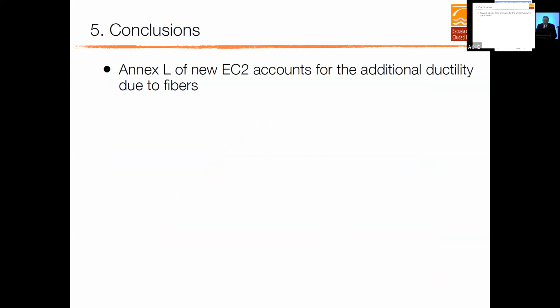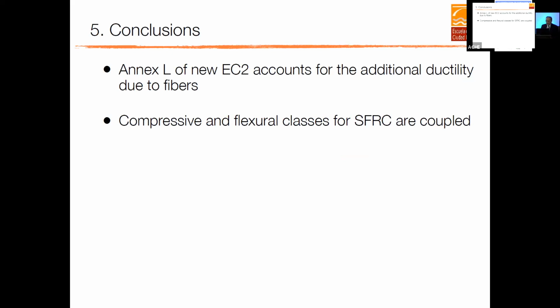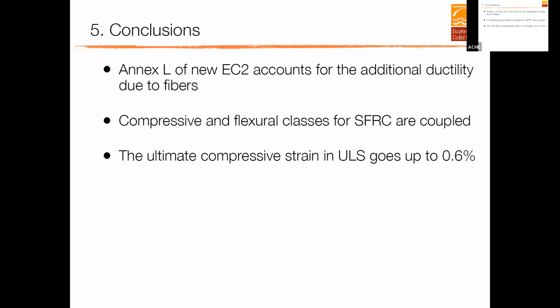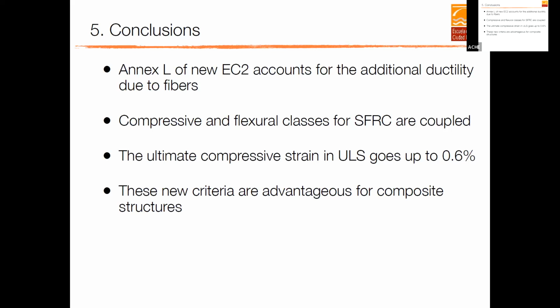So my conclusions are that the annex of the new Eurocode 2 accounts for the additional ductility due to fibers. Also, that compressive and flexural classes are coupled, even though I didn't explain this in detail, but it is in the paper. The ultimate compressive strain in the ultimate limit state goes up to 0.6%, which is a lot, and it can be more than that. And these new criteria are advantageous for composite structures and for any other structure.